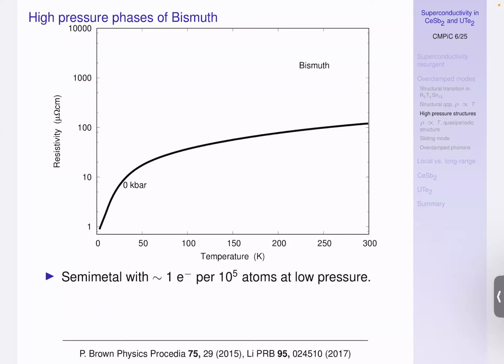The softening, yes, but the damping, I don't know how you would see it. So far, I think it's been seen. I certainly saw even old papers from the 70s in ferroelectrics and so on, where people did neutron scattering, and they could see clear evidence for phonon damping even in insulating materials. The question is, can it be so strong that a low-lying phonon gets altogether overdamped?